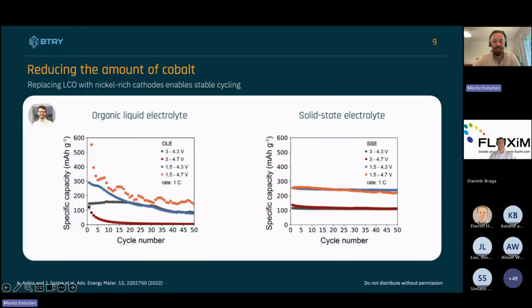Here you see more or less stable cycling performance. But as soon as you go to higher voltage, in this case 4.7, or lower voltage, in this case 1.5, you see strong degradation happening and side effects happening. This is because the liquid electrolyte degrades at these high and low voltages. It's not stable at these voltages anymore. If we now transition to a solid-state electrolyte, we see that we can stably cycle at an even extended voltage range. In this case, even getting more capacity out per weight if we go for 1.5 to 4.3 volts. And we can do this in a stable manner.